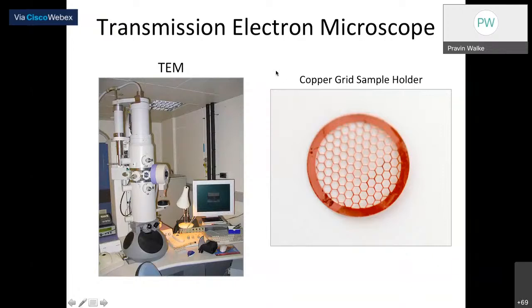So sample preparation for this TEM is quite delicate as compared to the SEM. In SEM, you can use a bigger sample, that's not a problem. But in the TEM, we cannot use a bigger sample. We have to have a thin enough sample, so that the electron gets transmitted through it. And in order to help those electrons transmit faster from the sample, this kind of conducting grid is required. Usually people use the copper grid, where we can put our specimen or sample, and we will pass the electron beam, right?